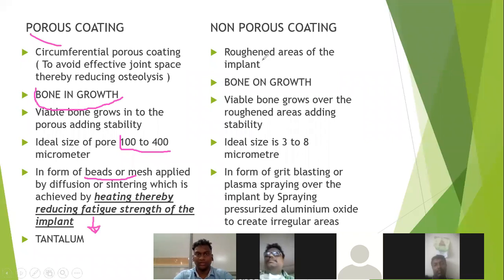For non-porous coating, bony ongrowth occurs. The viable bone grows over the roughened areas of the implant and offers stability. This is done by grit blasting and plasma spraying. We usually prefer non-porous coating materials.